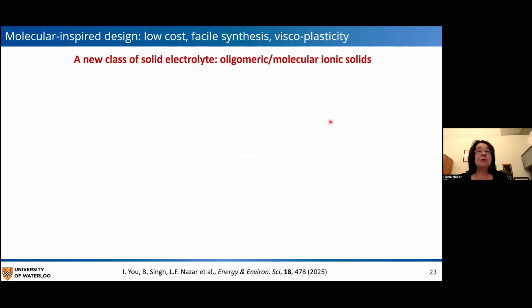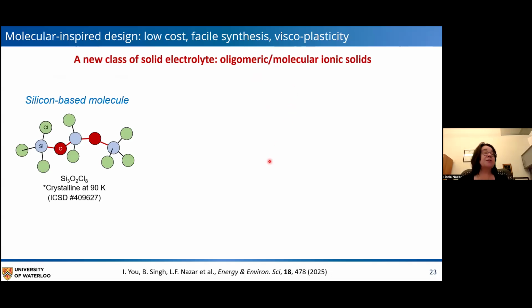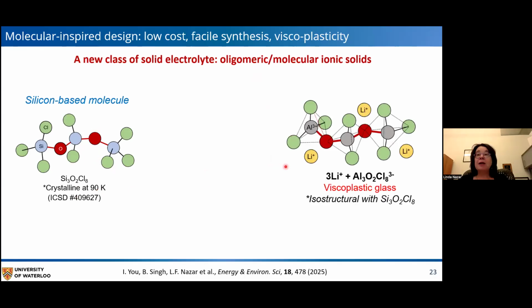So now I will switch gears again to move to the aluminum system, which is a new class of these solid electrolytes, which are effectively oligomeric molecular ionic solids. In some ways, they're similar to the sodium zirconium halides that I mentioned, except, of course, they're made by a very different process, and they're oxyhalides. So we took the concept of a silicon-based molecule, and we simply replaced the silicon with lithium and aluminum. This forms these oligomers, which we believe to be isostructural with their silicon analog.